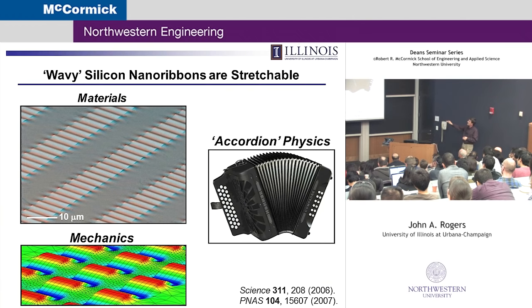So if I take this thing, I stretch it out this way, the amplitudes go down, the wavelengths go up in a way that accommodates an end-to-end overall strain deformation without creating substantial strains in the silicon itself. And so conceptually, you can think about this as a silicon accordion bellows. It turns out the mechanics is a lot more subtle than that. This gives you a good qualitative intuition, but this is a very non-trivial mechanics problem, it turns out.